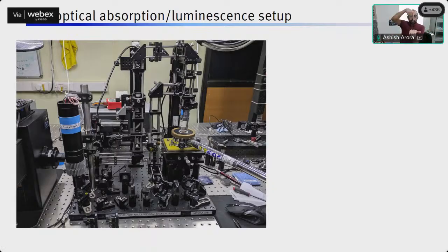Therefore, as soon as I move my sample using this XY stage under the light beam, that means now my sample is under the light beam, then I reflect a different amount of photons, and then I exactly would know how many photons are being reflected at different wavelengths as a function of wavelength, because I already know how many photons were there at different wavelengths by measuring the number of photons from the substrate. Now I check some unknown things such as my sample, such as my semiconductor, and I can measure the reflectance spectrum. This is the way reflectance spectrum is measured.